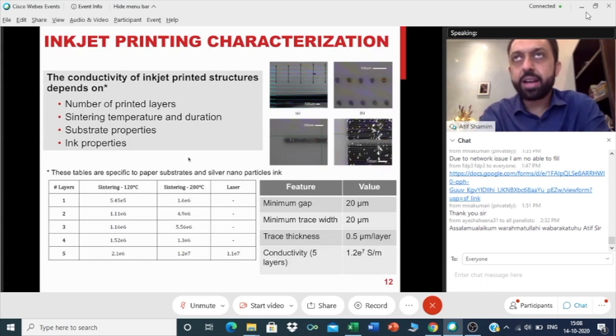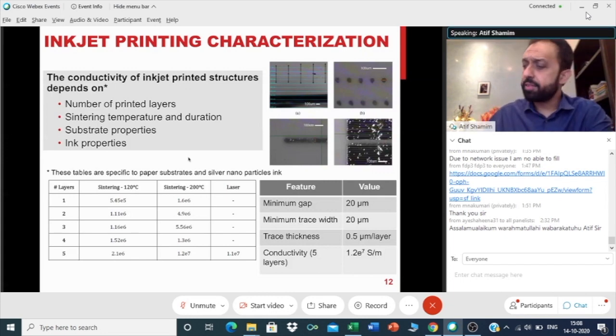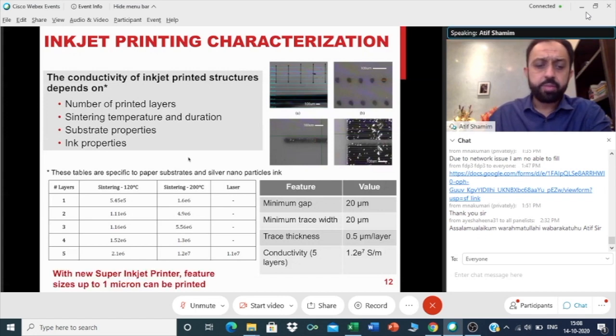For every layer, you will add a thickness of half a micron. And so this means that if you want, like, you're all RF guys, you know that due to skin depth, you need a certain thickness for conductors. Let's say if you need 3 microns, you can print 6 layers, and that will give you 3 microns. So you could print multiple layers. You could print even more, 20, 30 layers, whatever you want, and you could get the right thicknesses. Conductivity, you already talked about what kind of conductivity you could get from this.